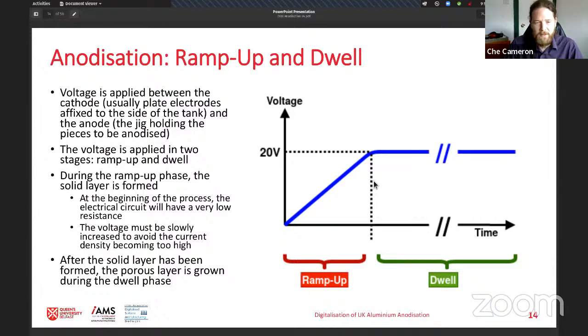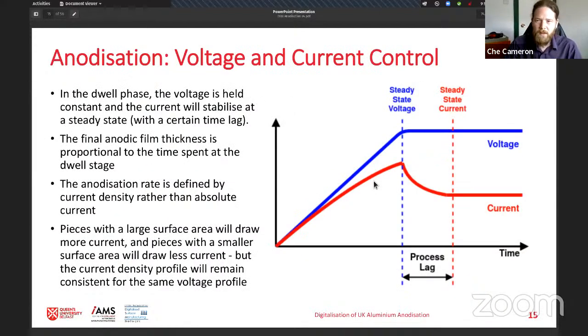The reason the voltage must be ramped is because at the start of the process, because you have bare metal in a conductive electrolyte, it's essentially a short circuit. So if you put the voltage too high, you will burn the metal essentially and cause problems. So the voltage is slowly increased, and as that oxide layer grows, which is non-conductive, the resistance of the circuit increases, and so you get a steady layer growth. After you have completed this ramping phase, you have grown your solid layer, and it's time to move on to growing that interesting porous layer. The porous layer is grown during the dwell phase, where the voltage is held at a steady state. And after a certain time lag, the current will also settle at a steady state.